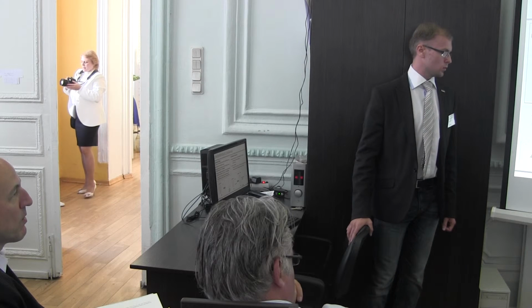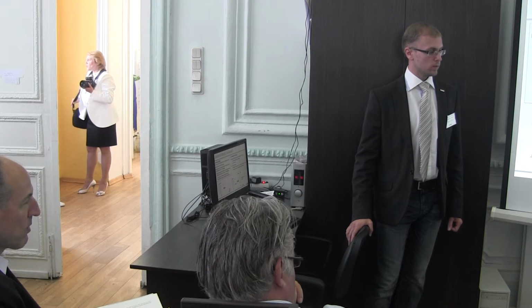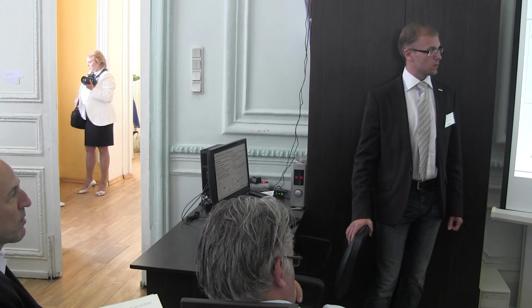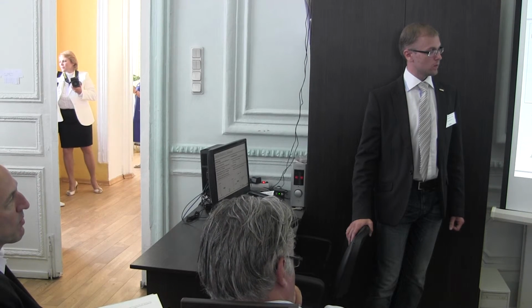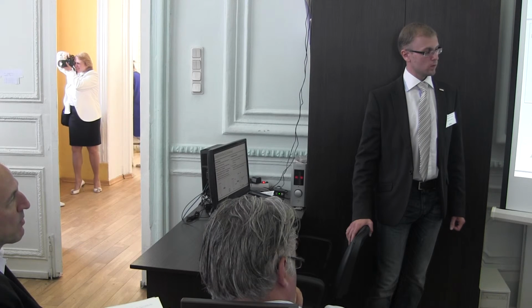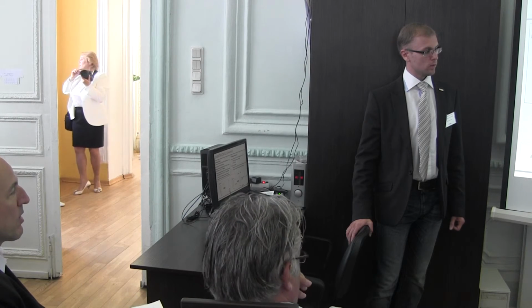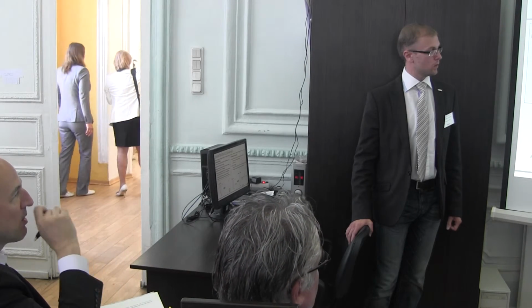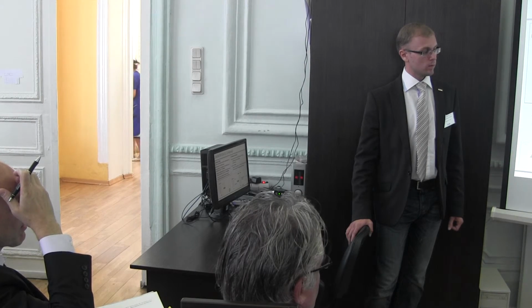And when this outer layer cracks, like this is cracked, we have a light source here, and our detector can detect the luminescence of aluminum oxide. When the aluminum oxide is still coated by the second layer, we are unable to detect luminescence.